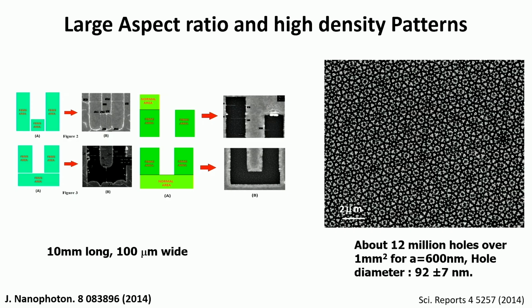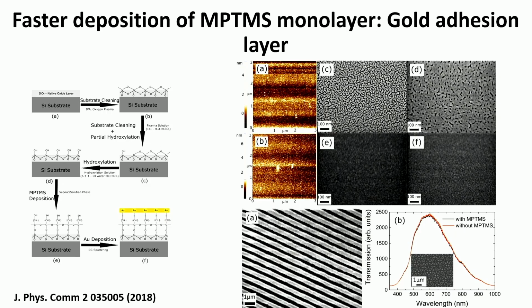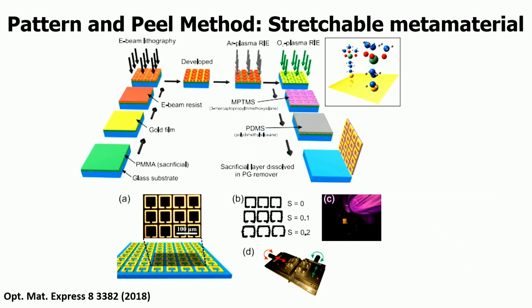These are meant for cavity structures for terahertz resonances, right? So this is another thing which we have developed, which is faster deposition of this polymer called MPTMS, which has a thiol bond at one end, which sticks to the gold, and an OH bond. Okay, last slide. The OH bond sticks to the substrate on the other end, right? So this has been used to make the stretchable metamaterial.